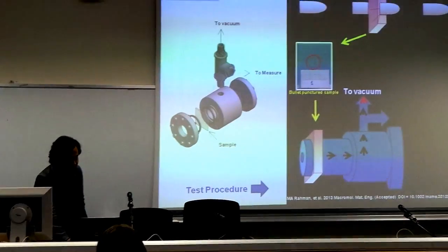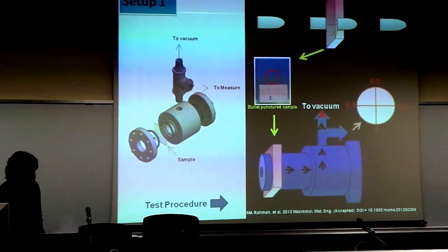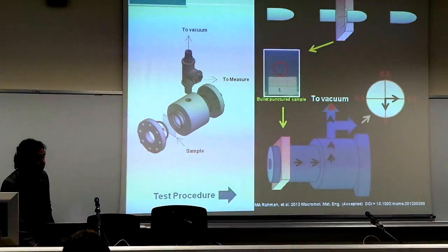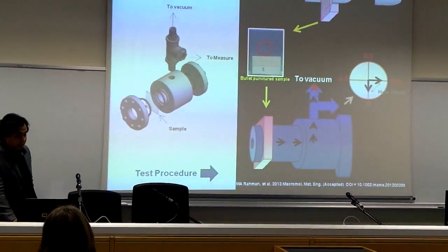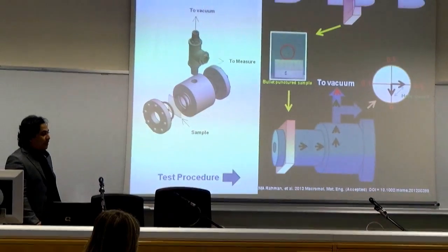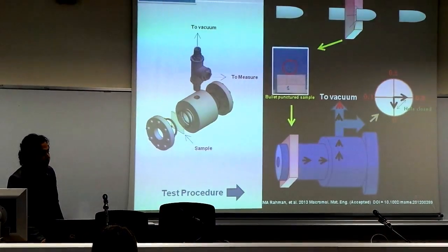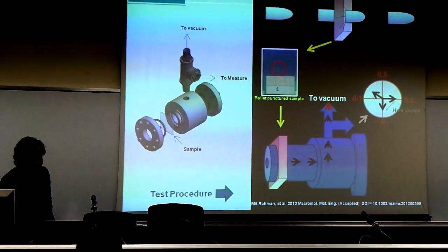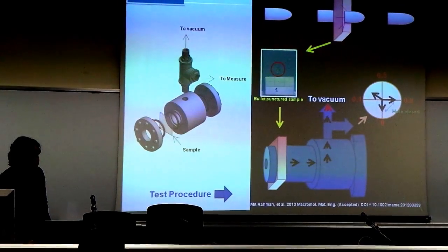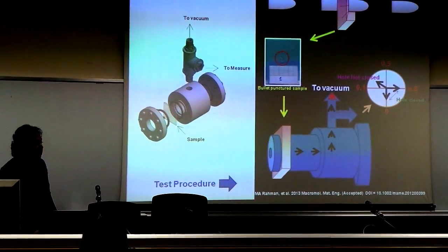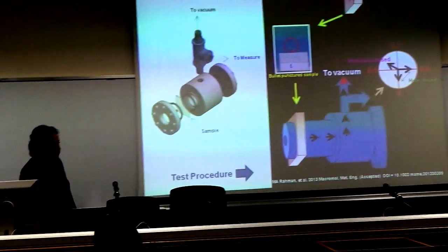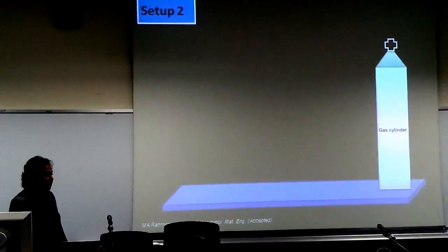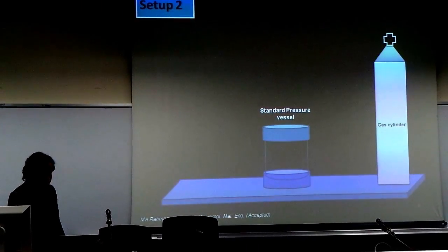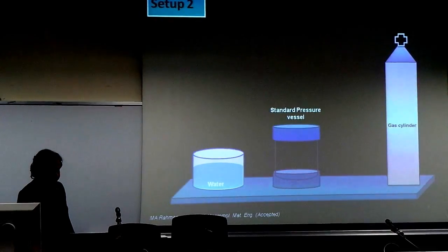I have a manometer. If the sample can maintain a pressure difference of 0.8 bar at the impact zone, it means the hole is closed, and that gives indication about the healing of the damaged zone. If I observe an immediate pressure decay, it means the hole is not closed, so the material failed to self-heal. The second setup consists of a gas cylinder, a standard pressure vessel, and a beaker containing water.